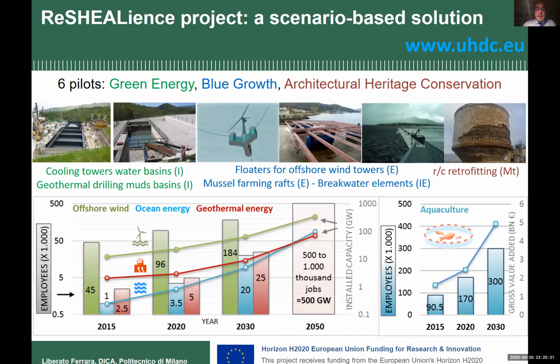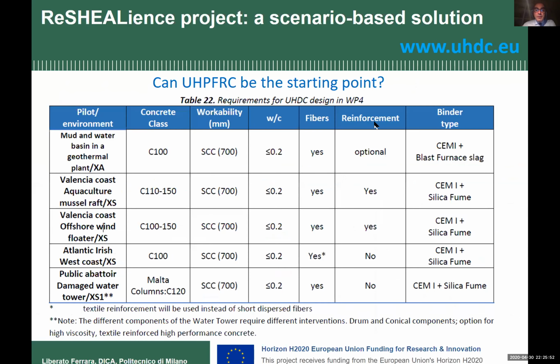And we started by assigning the performance requirements. For each of these structures, we have different requirements in terms of strength, workability, and the presence or absence of fibers, or whether we wanted to use conventional reinforcement, and the availability of constituent materials in terms of cement, supplementary cementitious materials, and so on. Also, to cast a new structure you need a consistency which may be different from the one needed to retrofit a structure.